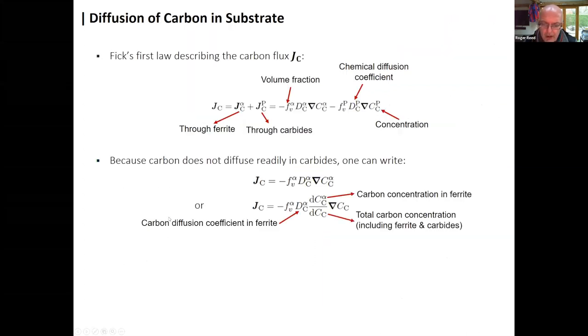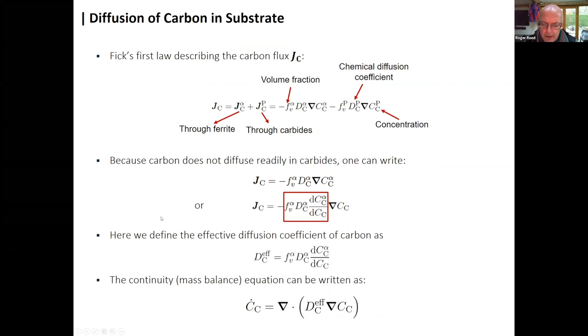Okay, so of course, Harry knows very well and taught me the mathematics of diffusion very nicely. So we can write down Fick's first law. We have to think in principle about diffusion of carbon through the ferrite. But in principle, of course, there's a large volume fraction of carbide. So you could imagine needing to consider also the flux through the carbides. But of course, as we all know, the carbon doesn't diffuse readily through carbide. So one can simplify things here.